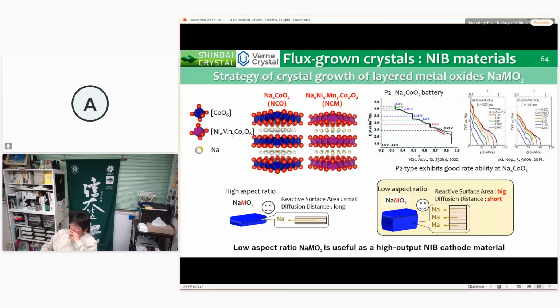Such P2 type compounds tend to grow in a high aspect ratio, usually in a plate shape based on a two-dimensional crystal structure. However, in this case, there is an issue of long diffusion distance of sodium ions. Therefore, we thought that if we could reduce the aspect ratio of the crystals, they could be used as a high output active material.